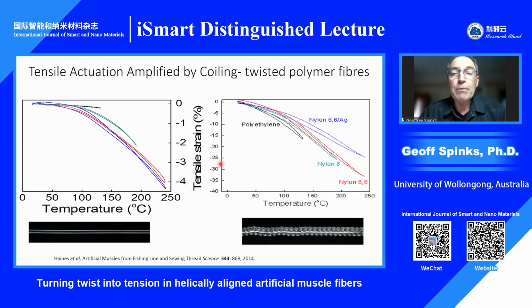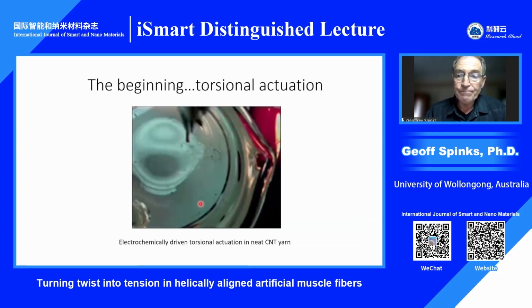And so there's an amplification going on. We know it's an amplification because, yes, there's certainly in a certain length of coil, there's, say, 3 times that length of fibre, but the amplification in strain is 10 times of the untwisted fibre. So there's certainly something else happening, which is producing a larger contraction on heating than just what we see in the as received fibre. And that's got something to do with the twisting and coiling.